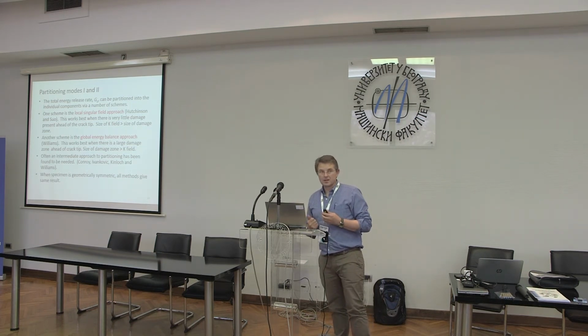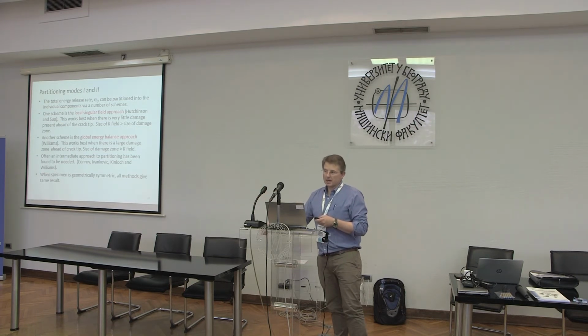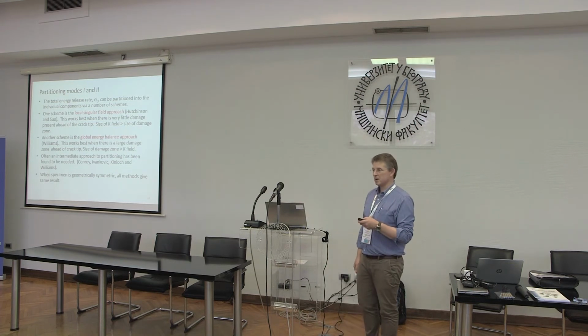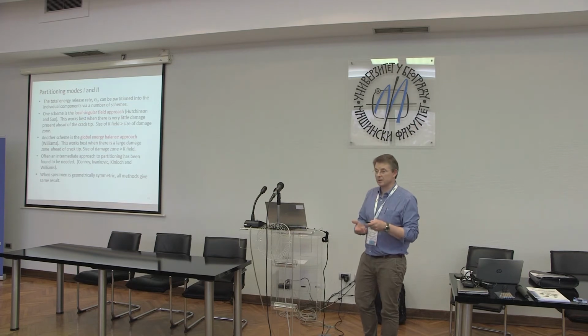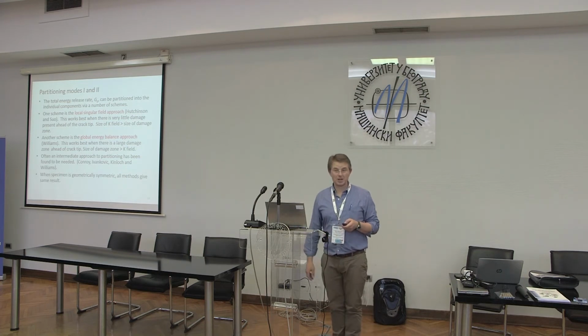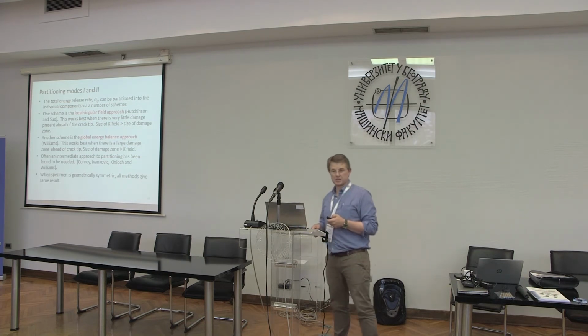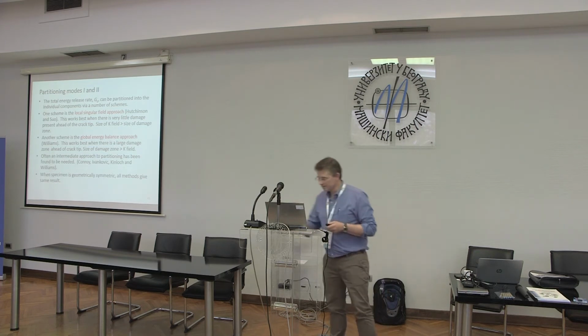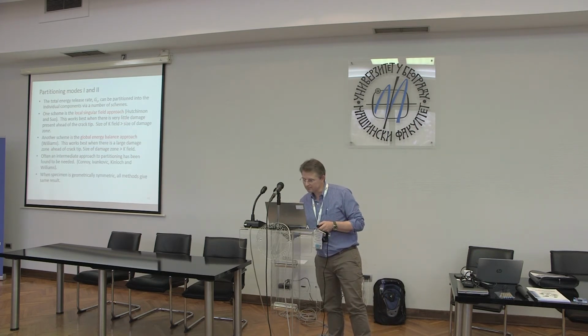And that sort of clarified a lot of the confusing literature there's been over about the last 20, 25 years on how best to partition. Because it's not always clear from a material whether it'll be singular or global. It's not intuitively obvious at all. You might think if the matrix of the material is brittle, it'll be singular. That might be wrong, because it depends not only on the toughness, it depends upon the other elastic properties of the system. So that is what I wanted to say about the partitioning.